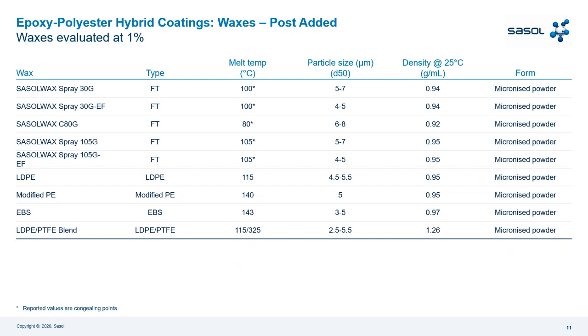Sasol wax Spray 30G, Sasol wax Spray 30GF, Sasol wax C80G, Sasol wax Spray 105G, Sasol wax Spray 105GF. These all come from a jet mill, are all Fischer-Tropsch, micronized wax. Then the melting point, you can see 100 for the 30 version, 80 for the C80G, and 105 for the Spray 105G and GF. Then, all micronized, as I mentioned, then LDPE wax, 115, micronized 4.5-5.5 micron; modified PE, in this case HDPE, melting point 140, 5 micron; EBS wax, melting point 143, particle size from 3 to 5 micron, micronized; and then PE wax and PTFE blend, as I mentioned before. This is post-added at 1%.